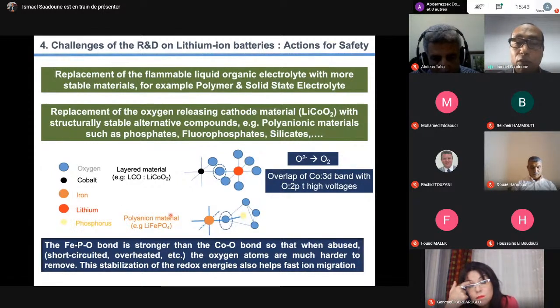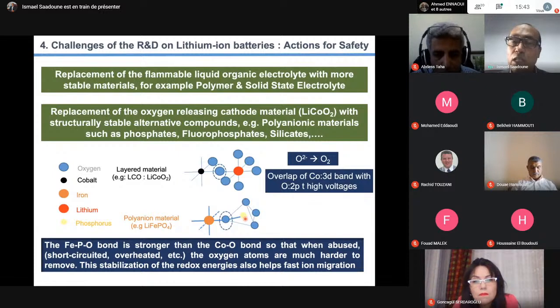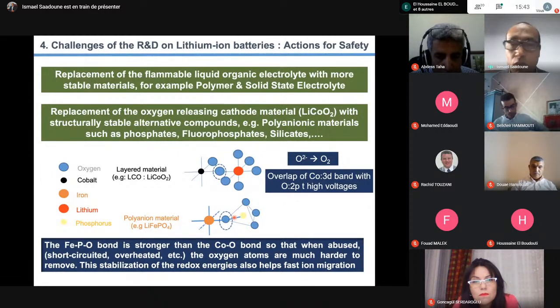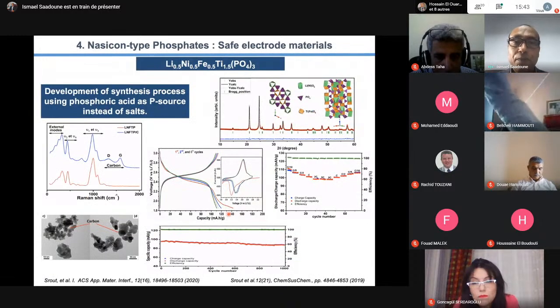In the phosphate, for example, we have this oxygen linked to phosphorus. It's very strong bonding, and we cannot release oxygen from the structure. That's why phosphates are much more safe than oxides from an application point of view.